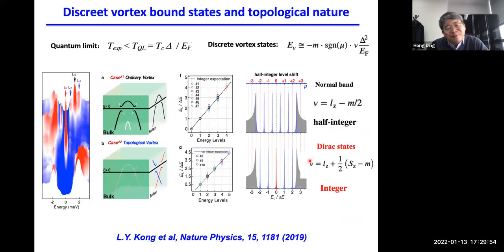But more importantly, it's not just the zero energy or the spatial profile, it's actually the discrete vortex bound states. So in our case, we reached the so-called quantum limit, where the quantum limit temperature is defined as Tc times the superconducting gap divided by EF. Since we have a small EF, and a large gap, and also a relatively high Tc, this quantum limit temperature is relatively high. So our experimental temperature is much lower. It's 400 millikelvin or even lower. So in this case, all of the vortex bound states become discrete, as described by this formula.